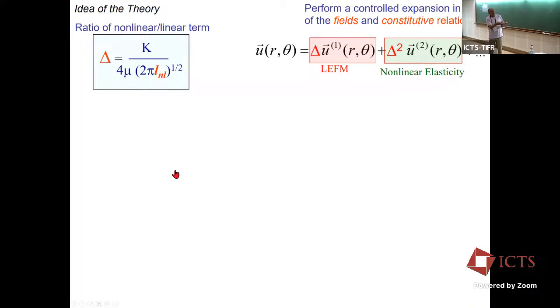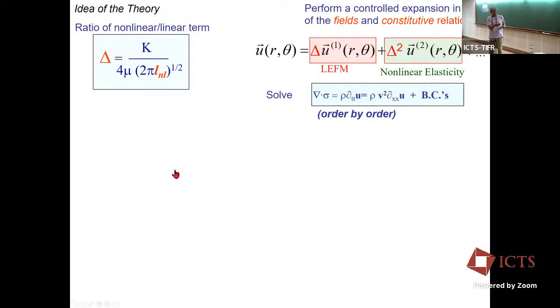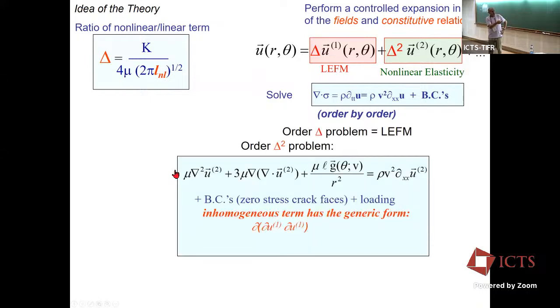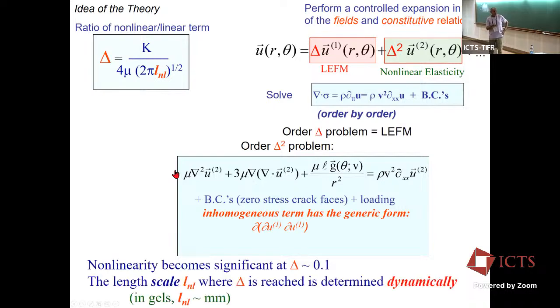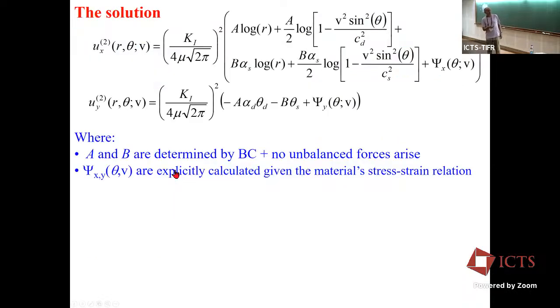And then he solved fracture mechanics. This is just Newton's law written so no one can understand. F equals ma for a field, and that's linear elastic fracture mechanics. He solved this problem, and then he used this solution to solve the second order problem, which looks much nastier, but it actually can be solved almost analytically. Nonlinearity becomes significant at some strain, in this case about 0.1. And this strain defines a length scale, how far away, and this length scale is determined dynamically. As the crack becomes faster and faster, this length scale depends on the instantaneous velocity of the crack. This is the solution.